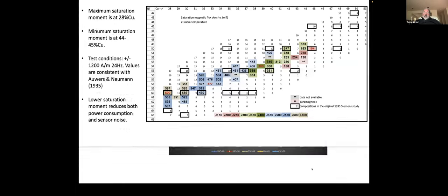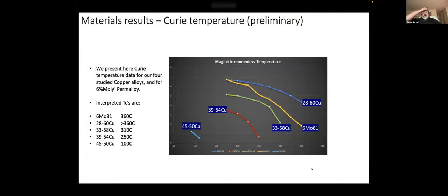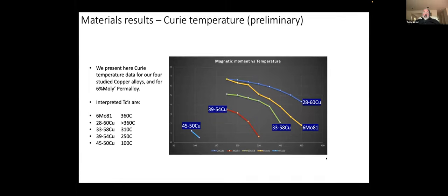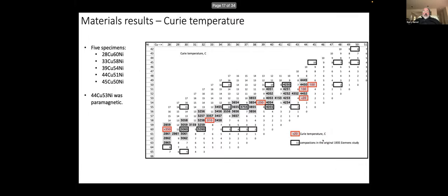Okay, next up, we're going to Curie temperature. They took the four alloys I pointed out before, added to that the 6% 81 nickel legacy material that came from Infinetics, and measured magnetic moment as a function of temperature and worked out what the Curie temperatures are. And I plotted them on one of these spreadsheets as well.